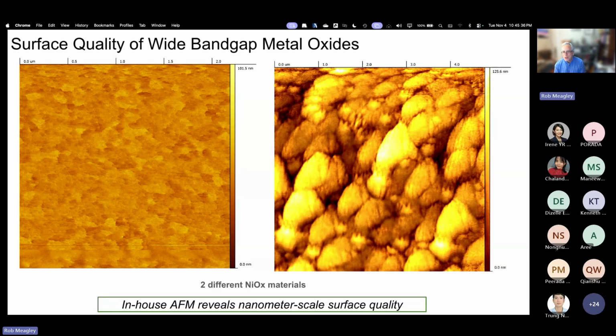Those conditions were somewhat unusual, but you can see some of these pits are really quite small. The smallest of these is down around 20 nanometers. And in this particular image, we were able to claim something like 10 nanometer resolution without too much difficulty, even though the surface itself was quite challenging.